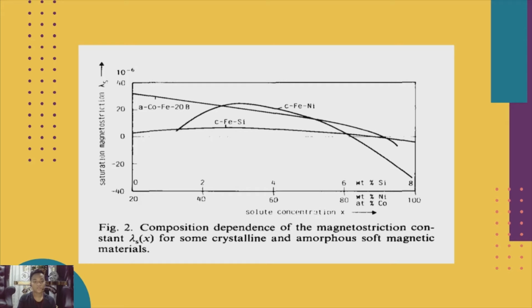For figure 2, composition dependence of the magnetostriction constant for some crystalline and amorphous soft magnetic materials. As illustrated in figure 2, the magnetostriction constant may pass through zero at a certain alloy composition, but this composition may not be favorable for other properties such as a small magnetocrystalline anisotropy.